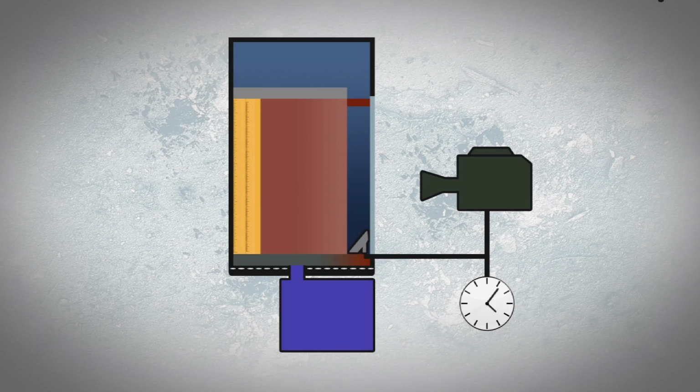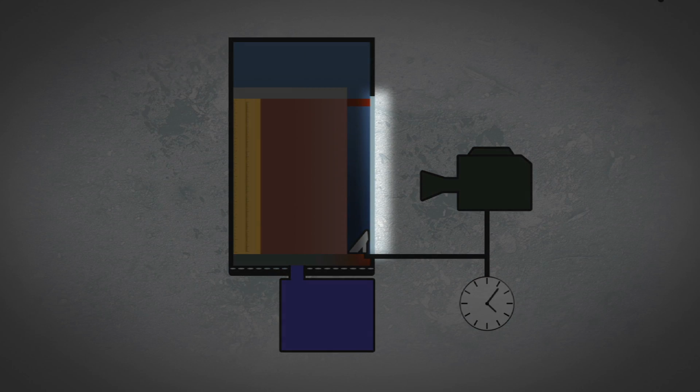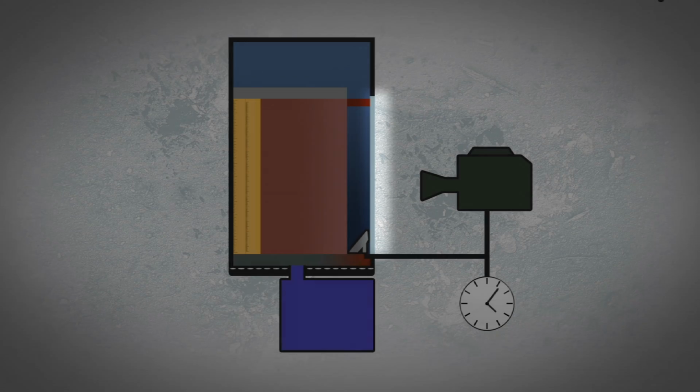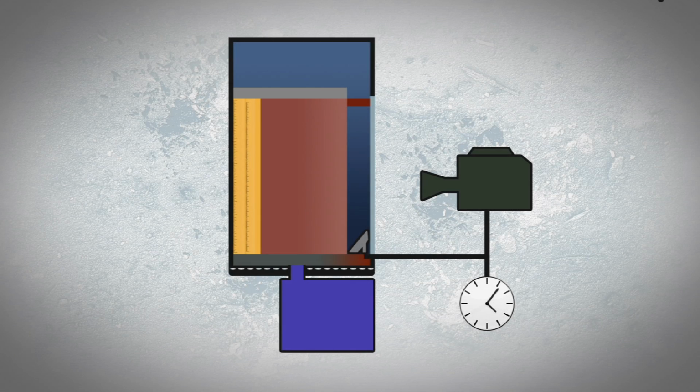The soil sample was placed in a temperature-controlled cabinet to simulate early winter conditions. An insulated window in front of the cabinet allowed observation. Granulated cork insulated the soil, so only the top was exposed to the cold air. The bottom of the cabinet was maintained at a constant temperature of 38 degrees. This simulated the natural situation that soil freezes from the top down.